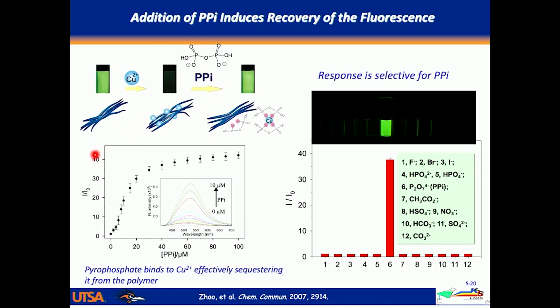And this is a titration experiment where now we're just measuring the fluorescence intensity as we add pyrophosphate, and you can see that it recovers, and it actually almost recovers 100% of the initial intensity before the copper was added. And it turns out it's rather selective. This is a bunch of different anions that were compared, and you can't see the vials because they're all quenched. They have copper in them. The only one that's unquenched or turned on is the one that has pyrophosphate in it. So it's a reasonably selective and quite sensitive sensor for pyrophosphate.